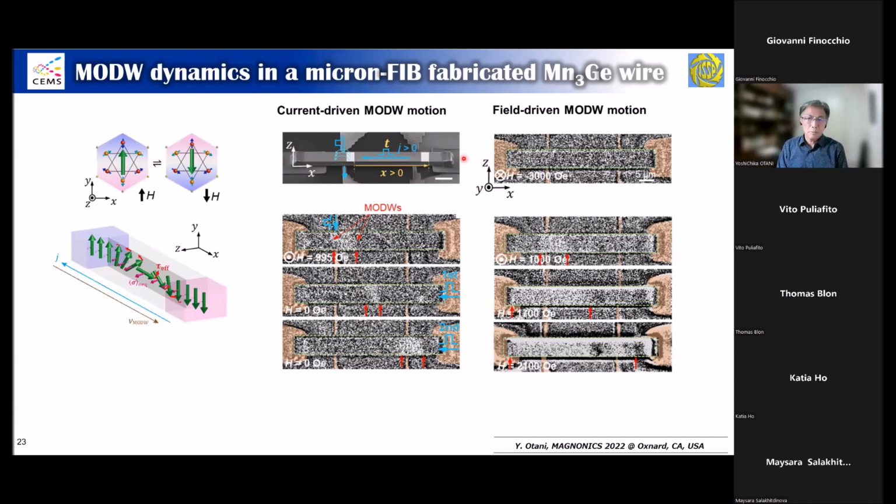The optical measurement is the real demonstration in this type of measurement, and we can see the nucleated domain wall. With an applied magnetic field perpendicular to the wire, we can nucleate these magnetic octupole domain walls, a pair of them, and in this case, this region is pointing upwards out of the plane.